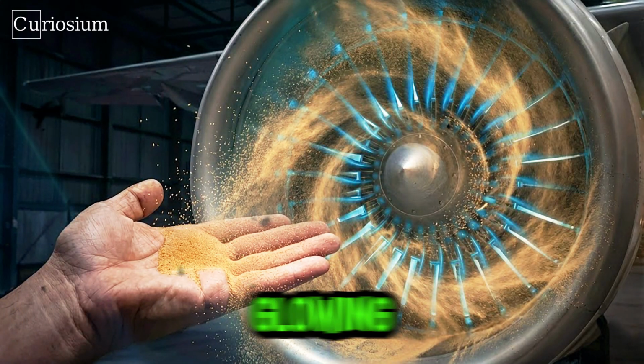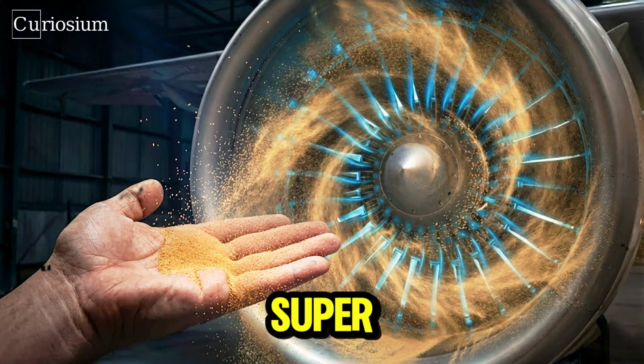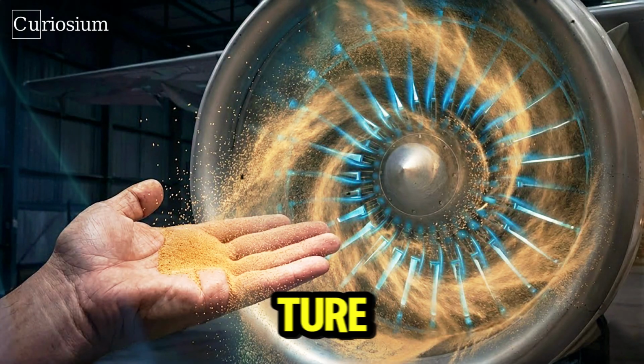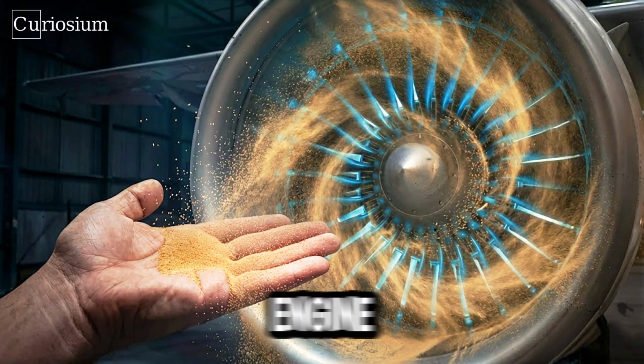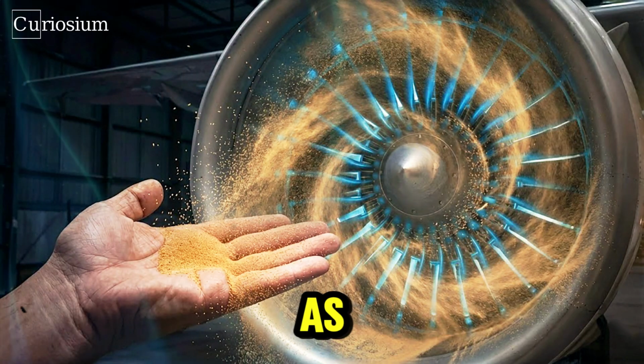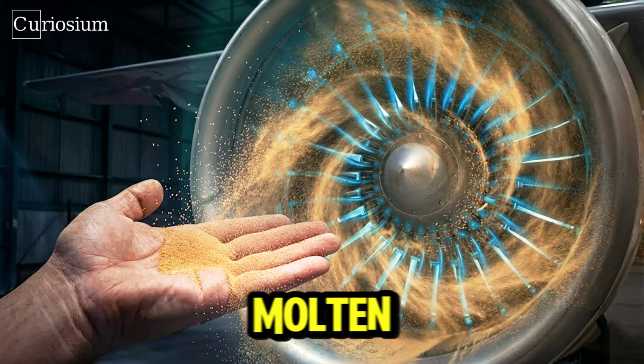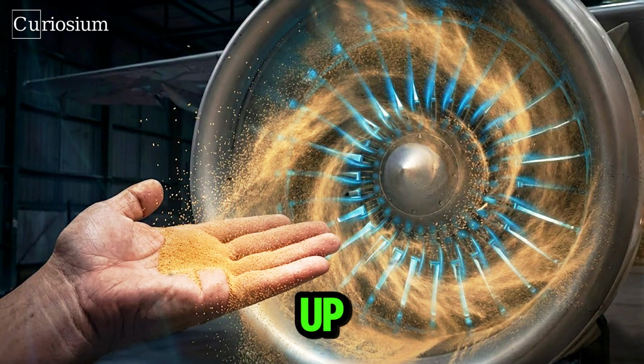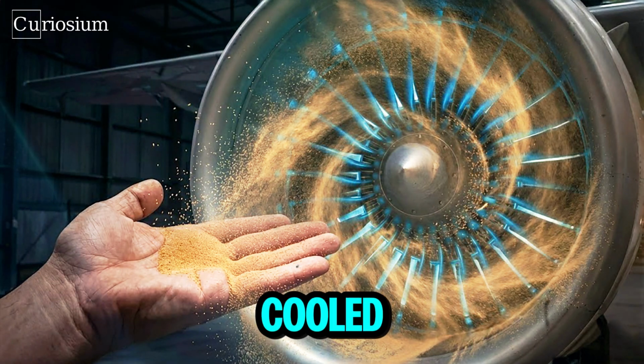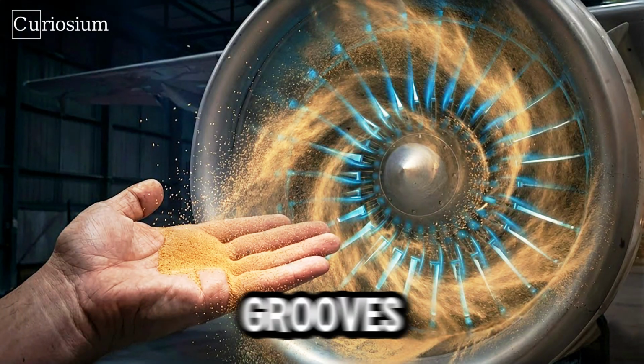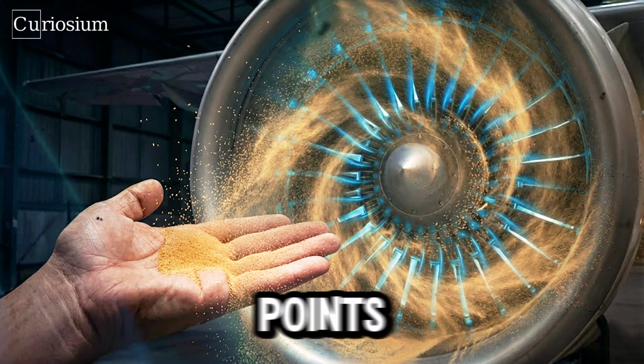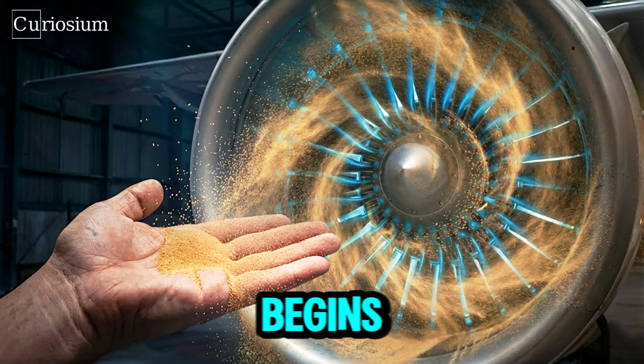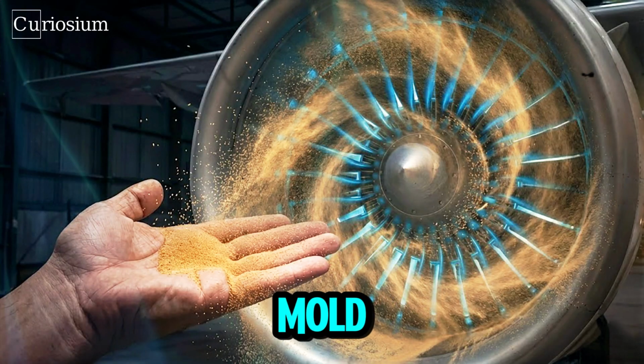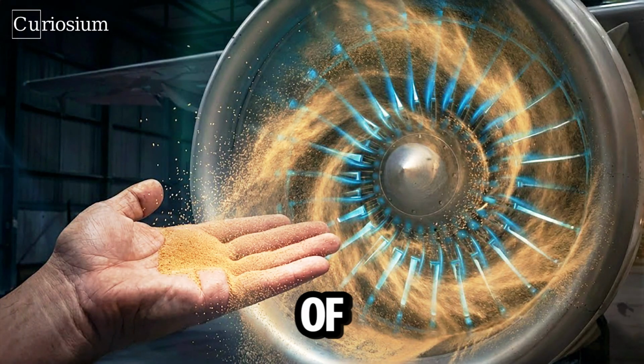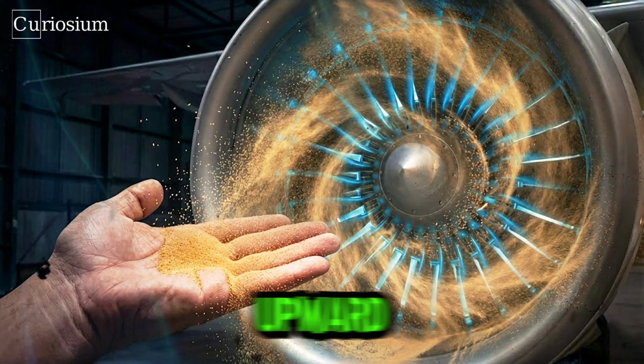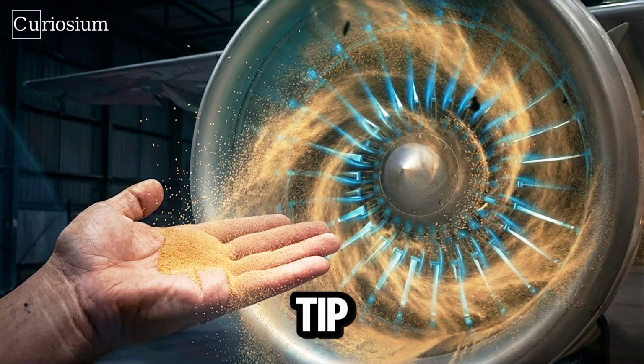Now imagine a vacuum furnace glowing with heat. The nickel superalloy is melted in that furnace at a temperature similar to what it will see inside an engine. The ceramic mold is heated as well and mounted vertically. The molten alloy fills the mold from the bottom up. At the very base sits a water-cooled copper plate, etched with small grooves. Those grooves act as starting points for crystals to form as the alloy begins to solidify. The whole mold is then slowly lowered out of the hot zone of the furnace. Solidification moves upward from the cold plate toward the tip of the blade.